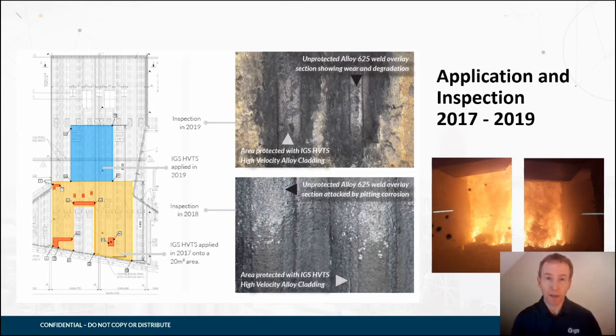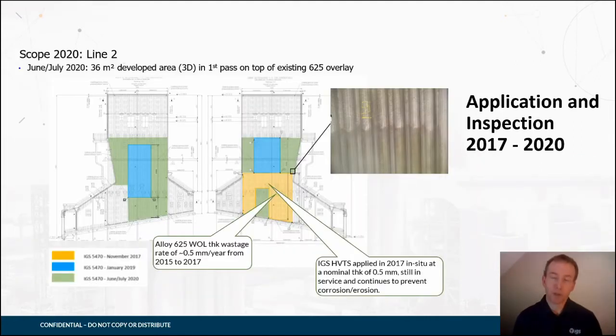After 1 year of operation in 2018, we went back in to do a full inspection, and what was obvious from that inspection was that the thermal spray was performing well and was protecting the alloy 625 underneath and preventing the ongoing degradation of the alloy 625 overlay. So at that point, the client decided to extend the application areas of the high velocity thermal spray into a wide area inside the unit. From the original application in 2017, we had the inspections in 2018, further application in 2019. And in 2020, again, we went back into the boilers to do some wider application and to further inspect the original applications that we did.